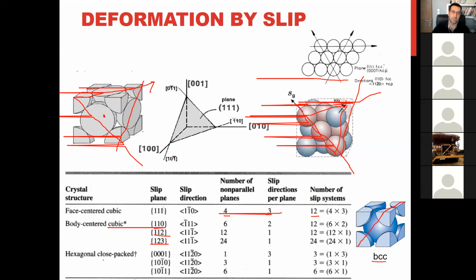And also for hexagonal close packed, the basal plane that we already talked about, this is a basal plane, which is similar to the 1, 1, 1 plane of the FCC. It is close packed. Inside this close packed plane, we have this direction, which is a slip direction also. And there are another two planes that we can consider as slip planes, in this direction. So finally, we have 12 slip systems in HCP crystals.